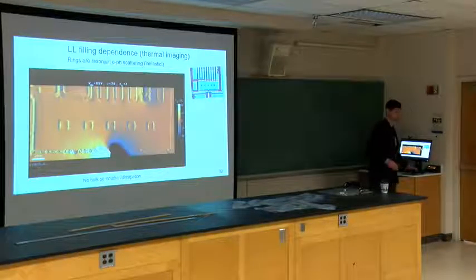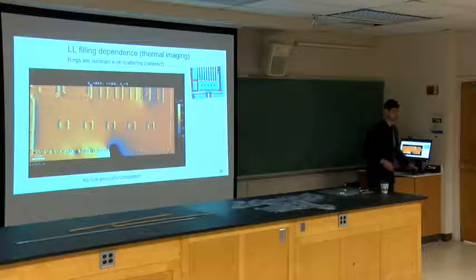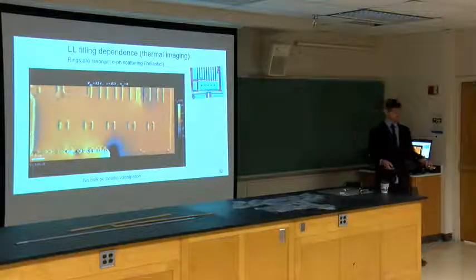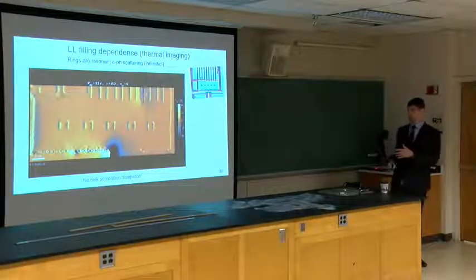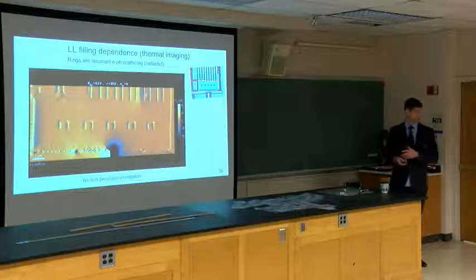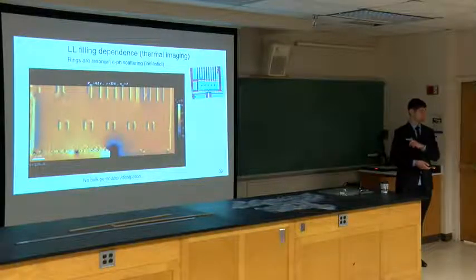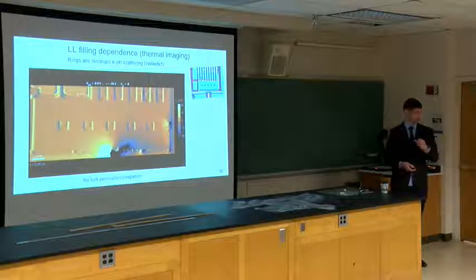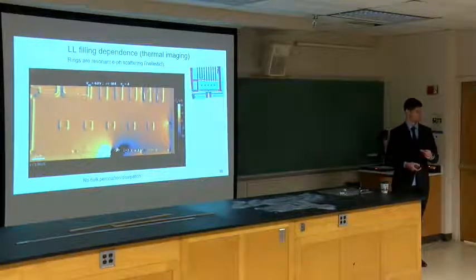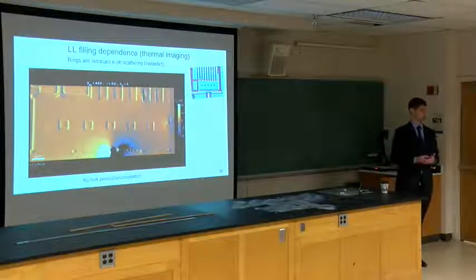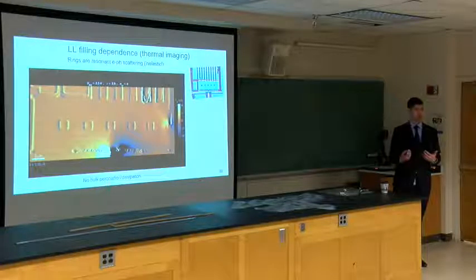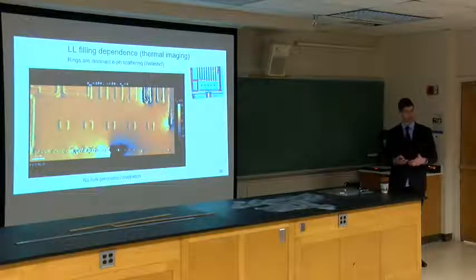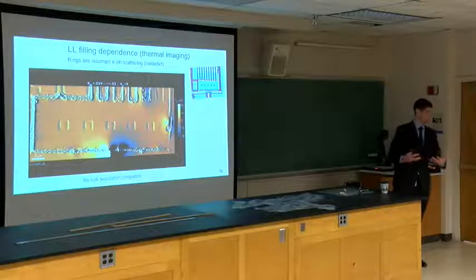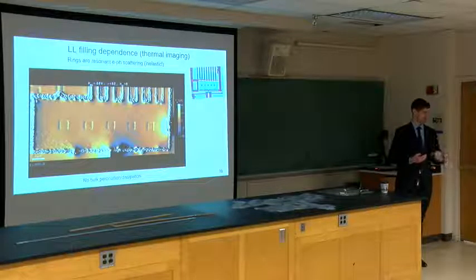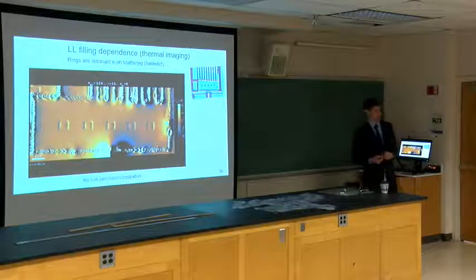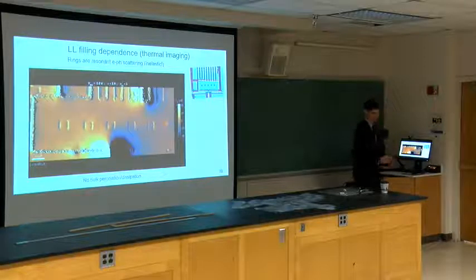How do you know the instrument isn't causing this effect? Your measurement might be causing what you measure. Well, we don't see it. You're perturbing the system with that. Oh yeah, exactly, and we mean to actually. We have to. Otherwise, you have to get to the right potential. Otherwise, the defect level wouldn't be in resonance. So we're seeing something that's there, but we're making it more visible basically by hitting it at a resonance behavior. So if that kind of makes sense.